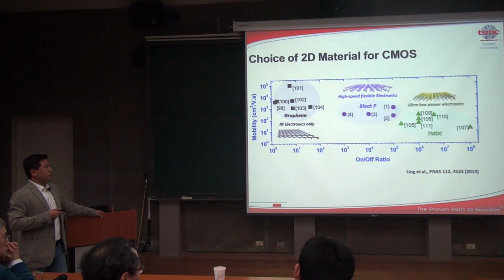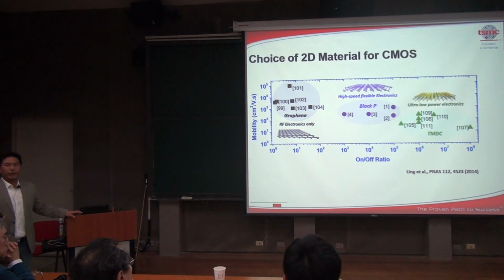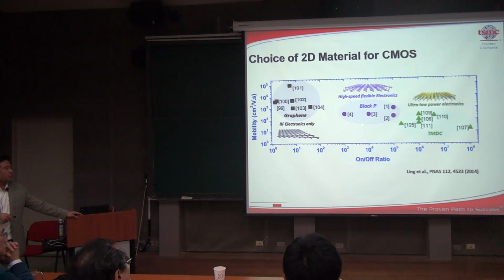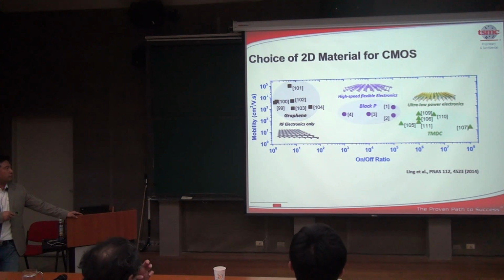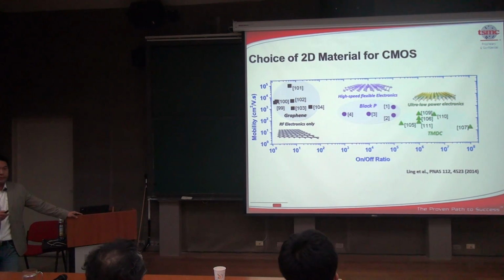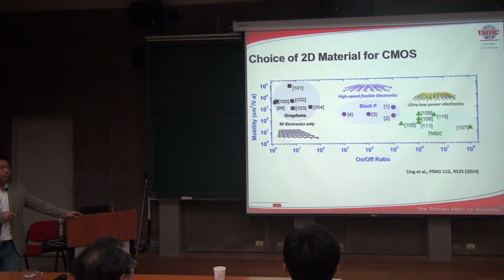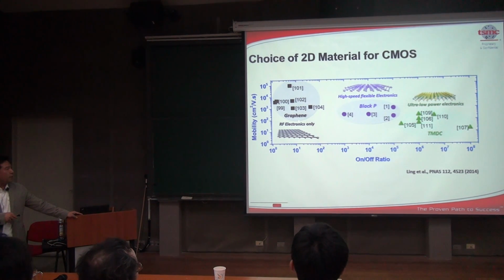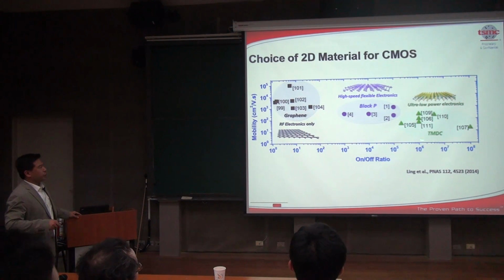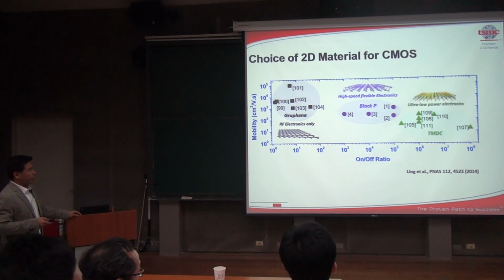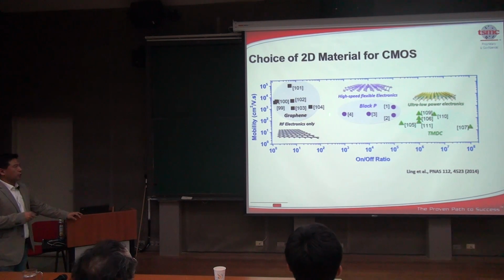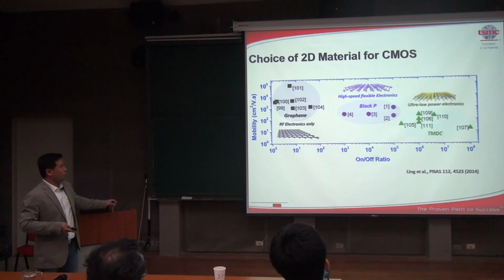Now in other 2D materials, it becomes relatively easy because they already come with a bandgap and with a decent mobility. Graphene even has a very good mobility, 10,000 to 100,000. By the way, silicon is roughly about 200 to 1,000. So this is definitely much, much higher than that of silicon. And black phosphorus and TMD materials have a bandgap, so they have a relatively larger on-off ratio, but because of the larger effective mass, the mobility is lower.